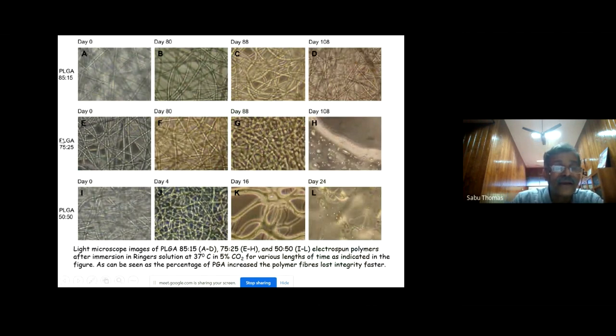PLGA. This is PLGA. PLGA is nothing but polylactic acid, glycolic acid, 85 to 15. This is actually microscopic images. Day 0, day 80, day 88, day 108. You will find that the copolymer of 50 to 50, more of glycolic acid, the scaffold disappears much faster. Look at this. After 108 days, you don't see any fiber here. If you look at 85 to 15, less amount of glycolic acid, you still see the fiber. So when you make copolymers, you can control the extent of degradation by controlling the composition.